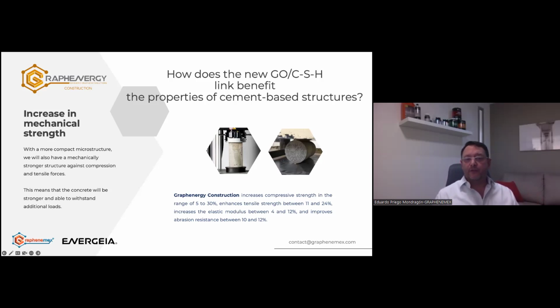Graphene construction increases compressive strength in the range of 5 to 30%. It also enhances tensile strength between 11 and 24%. It increases the elastic modulus between 4 and 12% and improves abrasion resistance between 10 and 12%. As I just told you, there is a range of results that are obtained, and this range is due to the numerous variables that concrete designs can have.